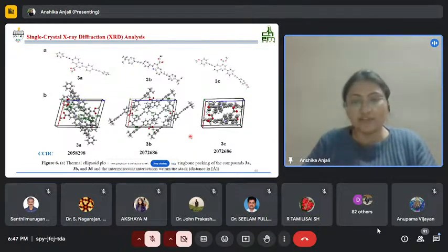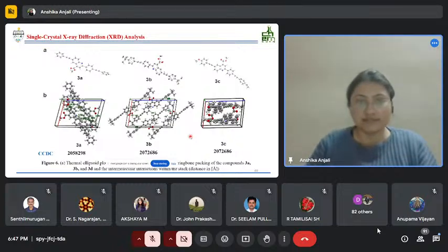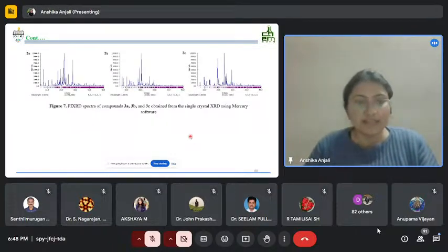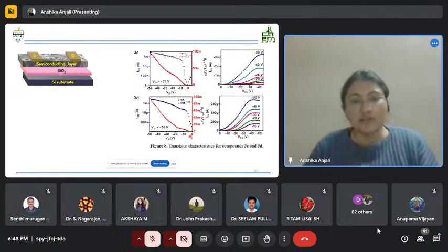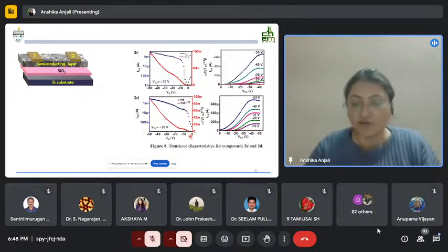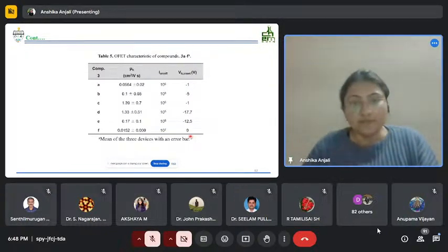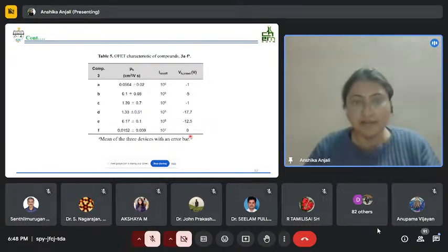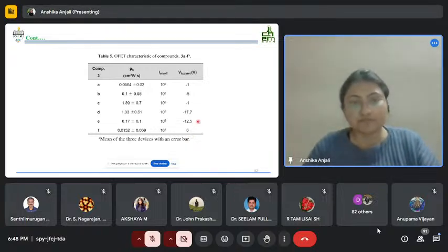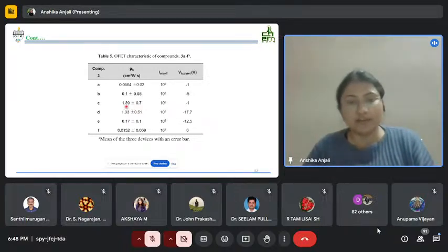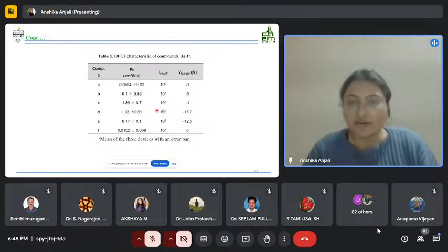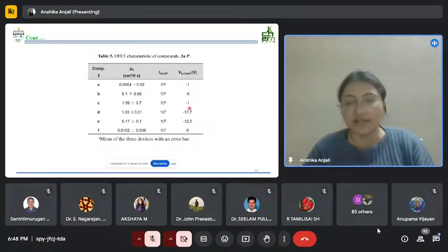We did obtain a single crystal for them, and these are the single crystal XRD studies. This is the PXRD spectra that we have recorded for these compounds. For these compounds, we have fabricated OFET devices and recorded their transistor characteristic curves. These compounds have exhibited nice hole mobility. Here the compound 3C, with 4-methoxyphenyl as the end terminal, resulted in the highest hole mobility of 1.39 centimeters square per volt per second, with a current on-off ratio of 10 raised to power 6 and a threshold voltage of -1.